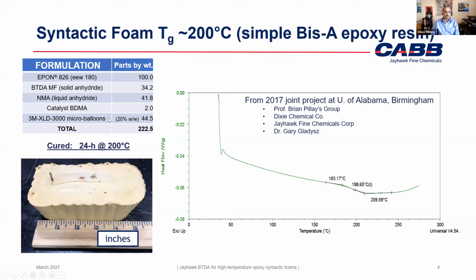We use microbubbles at 20% by weight in the overall formulation. And you will notice that with, again, a very simple Bis-A epoxy resin, we were able to get a TG of about 200 Celsius. And then, we actually had other temperatures we were able to reach based on what we were trying to achieve in the project. There was some compressive strength data, flexural strength data generated as well.